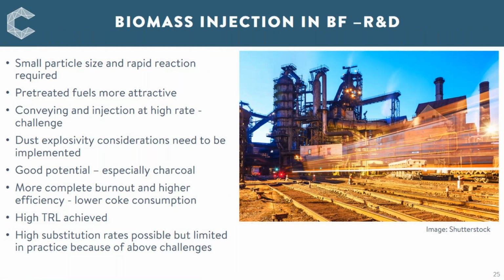Another area that has had a lot of research and development, and is actually at one of the highest technology readiness levels, is injection of biomass or charcoal into the blast furnace, at the base of the blast furnace. And here you want a small particle size, it's pulverized, and you want rapid reaction to release the heat quickly. And actually pre-treated fuels, thermally pre-treated fuels like torrefied fuels and charcoals, have more attractive calorific value and grindability than biomass itself. So there's a lot of interest here in using torrefied materials, biochars, and other types of pre-treated biomass, hydrothermal carbonisation, and so on.